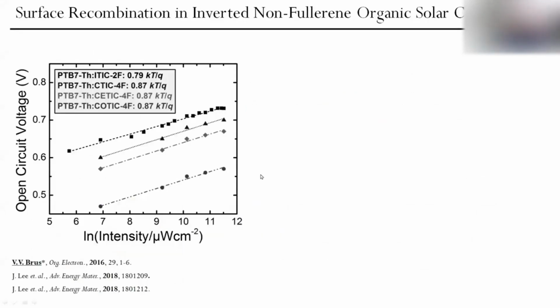However, it's not enough, because recently, when we got access to this new type of acceptors, non-fullerene acceptors, which I mentioned earlier, they helped us to increase significantly the performance of organic solar cells. We noticed that this slope, open circuit voltage versus light intensity, is actually smaller than unity. So that is described by the presence of surface recombination. As I mentioned before, there are two types of non-geminate recombination, bimolecular and trap-assisted.